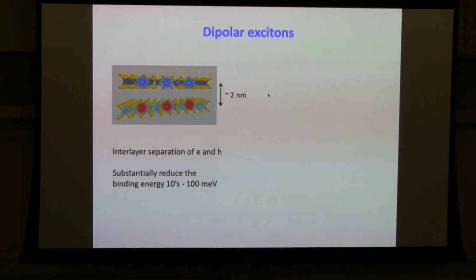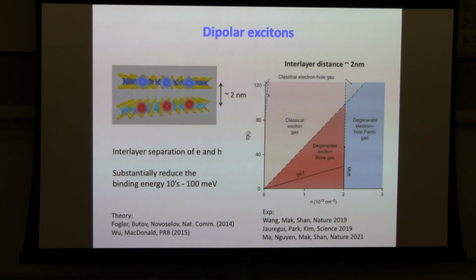But it's still substantial enough that when the theorists calculate the phase diagram for this non-interacting boson gas under this setting of a 2 nanometer separation of the electron and hole layer, you can get a degeneracy temperature still up to about 100 Kelvin and a BKT transition temperature that's about 30 Kelvin. So still a pretty high temperature scale for the exciton superfluidity, not 1000 Kelvin, but still substantial.